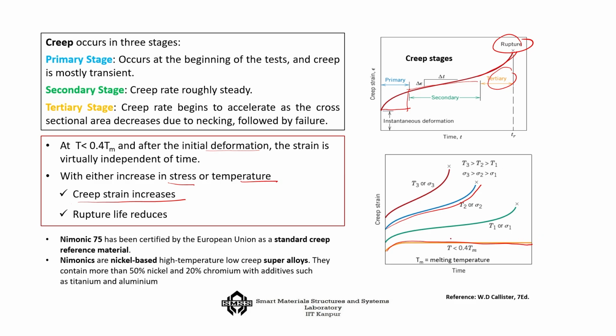So, you will see the instantaneous deformation that will remain steady. But as the temperature is increasing, you are finding shorter and shorter life of the system in terms of the rupture. Now, how do we compare the creep of a material? So, we use a comparable material called Nimonic 75 as a standard creep reference material. So, with respect to Nimonic, which, like any nickel based high temperature superalloy, has low creep, with respect to that we can measure what is the creep in our system.